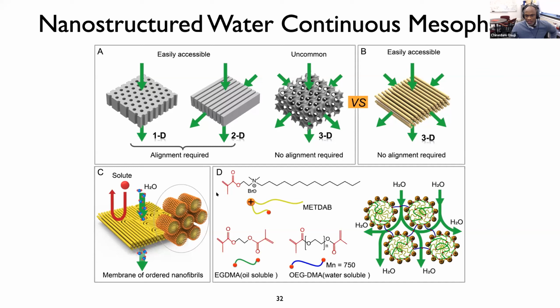Okay, and so the mesophase that we used was one that was formed by this polymerizable cationic surfactant called METDAB. And of course, if I was offering this project to a bright-eyed graduate student, they would probably tell me, Professor Osuji, this is interesting, but I think this won't work because if you polymerize these cylinders, what's to keep them from all floating apart in excess water once you're trying to use the system as a membrane? And of course, and this was the serendipitous part, the mechanical integrity, the coherence of this material is in fact guaranteed by two things. One, there are topological interactions, if you will, across the material because of the presence of defects, right? And so in the same way as an onion, in some sense, is held together by interlocking layers, these cylinders are held together topologically, and they're interconnected physically in some way.